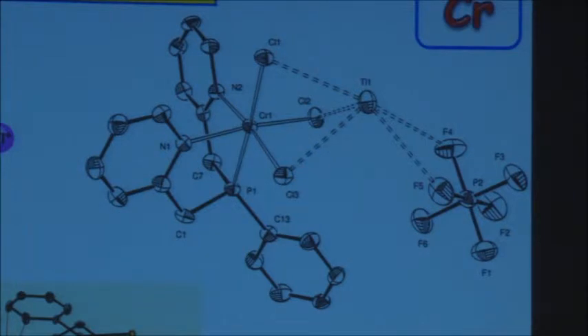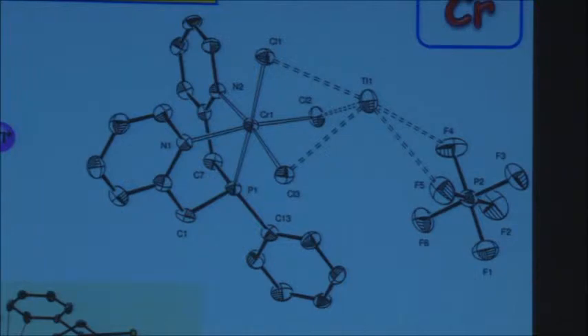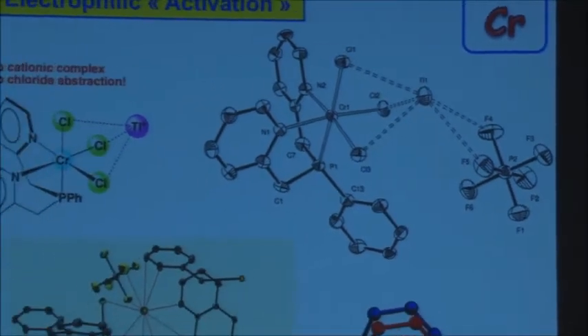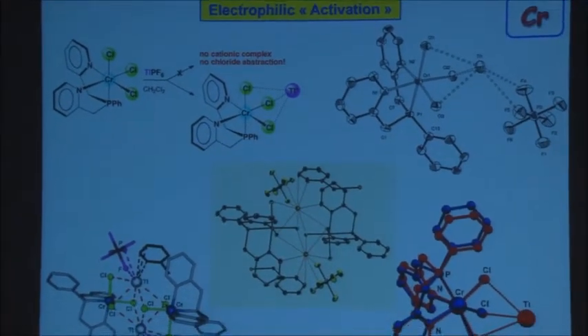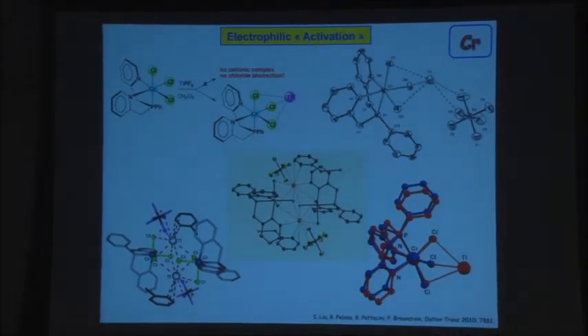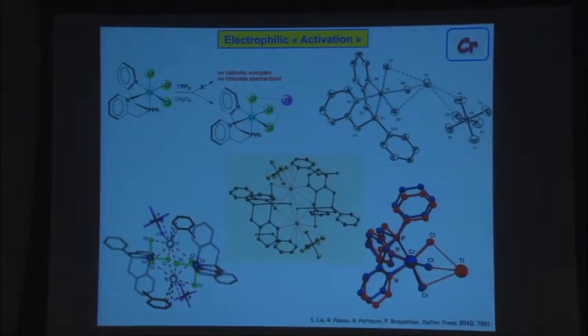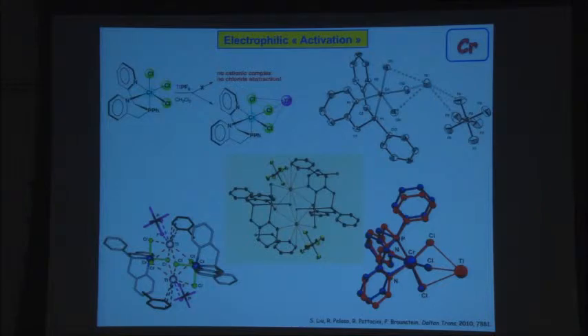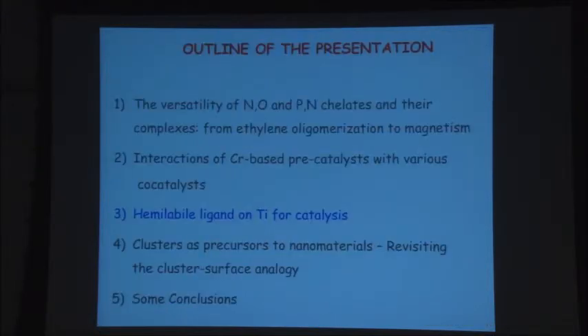The message is here, if you use typical chloride abstractors, and this is not the first example in our hands, they don't always behave as chloride abstractors. And that very much depends on the solvent. In dichloromethane, often you add the electrophile to the substance instead of removing the chloride. If you go to acetone, a totally different game. So again, this should trigger your curiosity. We should always be careful and cautious about what we say, because there are always exceptions. But these can be very important, of course, in terms of reactivity and catalysis.